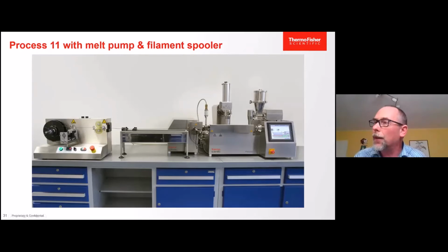We see again, like in the previous video, main feed, secondary feed on the twin screw extruder. What is new is a melt pump. Sorry, I should use a pointer over here. So main feed, secondary feed, the twin screw extrusion system, a melt pump, and running either through a water bath, or in this case, just in air for cooling, through a laser gauge for checking the diameter, and a small spooling system to wind up this coil for 3D printing.